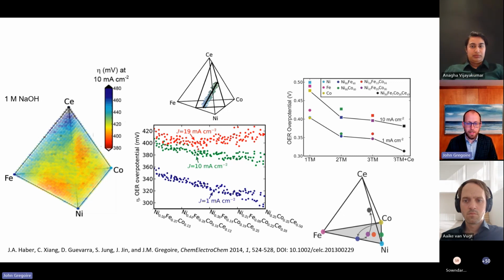If we look at this data in different ways, say, if you have single transition metals, you can add a second one and get a big jump down in overpotential, which is very desirable. If you add a third transition metal, you're at diminishing returns. But then if you add the cerium, you can get another jump down again. So this is an example of how marching into high order composition spaces really gives you these emerging properties that we're looking for in materials discovery.